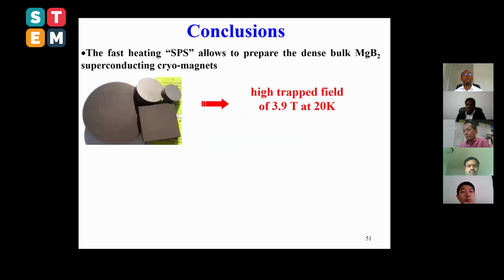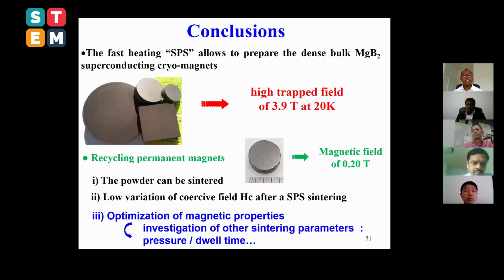Okay, let me come to the conclusion. The fast heating SPS allows us to prepare dense bulk magnesium diboride cryomagnets, which were able to trap roughly 4 Tesla at 20 K. Then regarding the permanent magnet, the powder can be sintered. This is what we demonstrated in the first part of our ongoing project. And we also observe some low variation of coercive field HC after SPS sintering. In the recycling powder permanent magnet, we were able to obtain 0.2 Tesla.